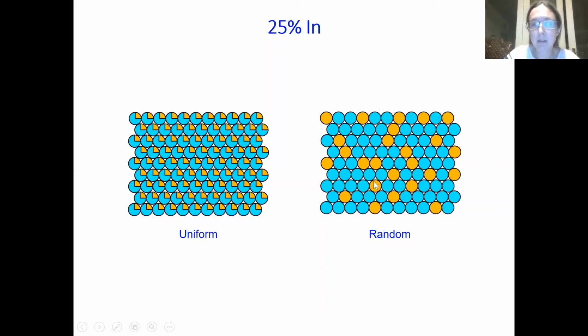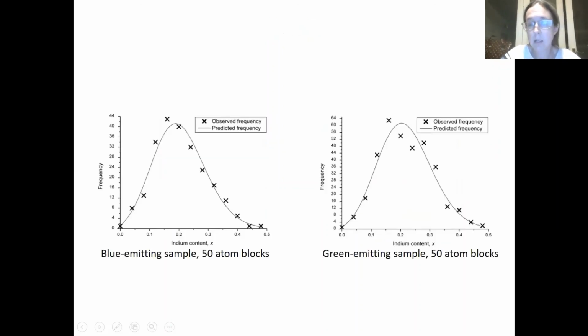We expect them to be arranged at random, okay? So that doesn't mean that you always have kind of perfectly spread out indium atoms. Sometimes if you roll a dice 10 times, you get 10 sixes. So sometimes you get the odd row of indium atoms all next to each other, and sometimes they're a bit more spread out. That's kind of what a random alloy looks like. So we can statistically analyze whether an alloy is really random by essentially chopping the alloy up into small blocks, here 50 atom blocks, and measuring the composition of each block.